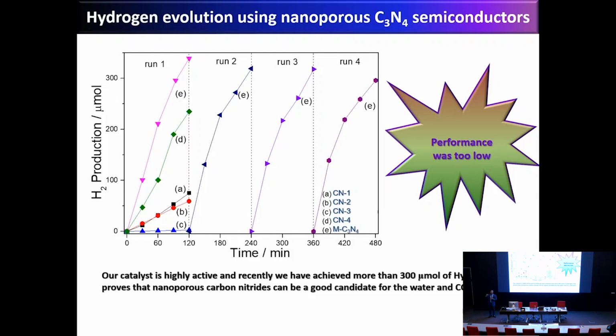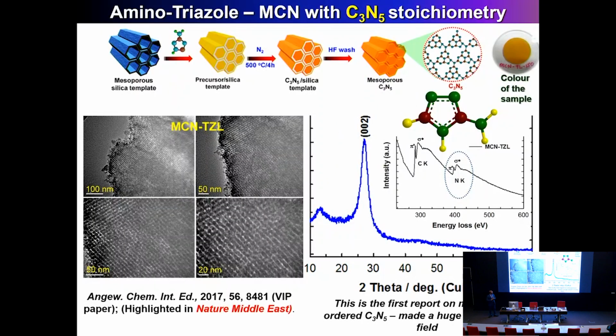So to overcome these difficulties, what we have done is to change the band gap of this carbon nitride material. And how we have done is, instead of diaminotriazine, we used diaminotriazole. So that has got 2 carbon atoms and 4 nitrogen atoms. And again, we integrated this one with the mesoporous SBA-15 template with the well-ordered porous structures. And we reduced the temperature a little bit from 550 to 500 degrees centigrade and removed the silica template by HF or sodium hydroxide, and you could get carbon nitride with the C₃N₅, and this was calculated with the CHN